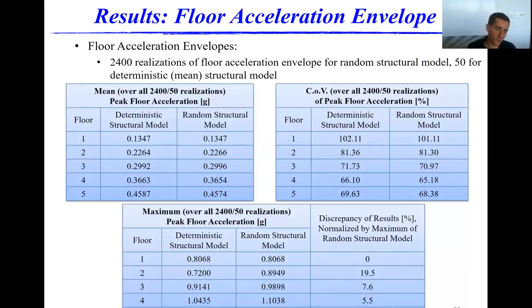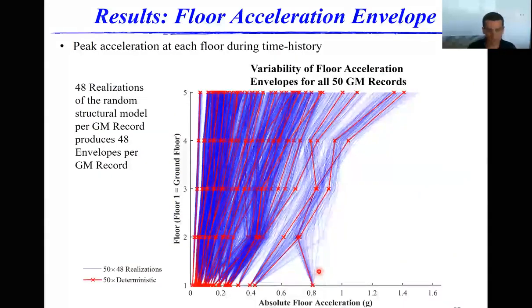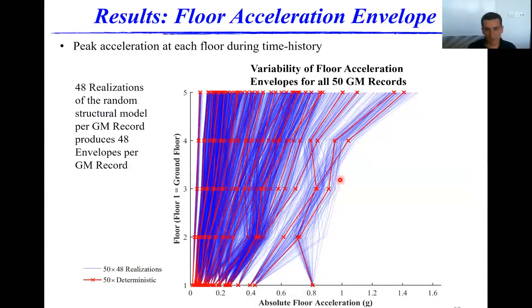And I also show the maximum over all 2,400 and the maximum over all 50 deterministic runs. And we see that the maximum is higher for all of the random cases, as we expected, the absolute maximum, which corresponds out here. So these versus this red one right here.